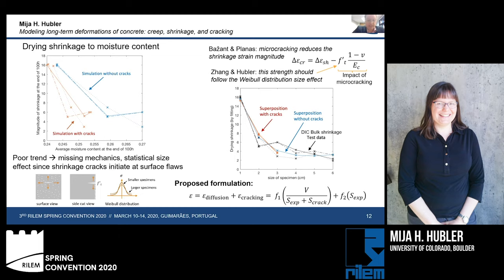Technically, there is a statistical size effect that affects this problem, because each shrinkage crack must start on the surface of the sample because of the gradient of the properties and the moisture that we see. In order for that crack to open, it will find a flaw, and at that flaw will then start to initiate the cracking. The statistical size effect associated with surface flaws follows a Weibull distribution.